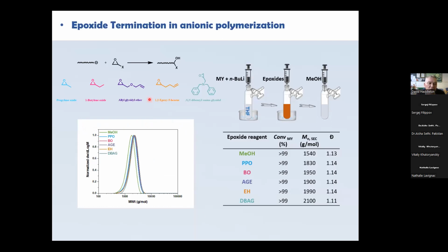We do that polymerization. Control of the end group is actually trivial in anionic. You'll see many papers in radical where we did this, and we ended up with 75% end group modification. Isn't this really good? Well, here you get 100%, really. So we're targeting relatively low molecular weight because it's dispersants. So 2000, we get full conversion. We're not using high vacuum lines, we're just using normal glassware, and so these dispersants are pretty good.